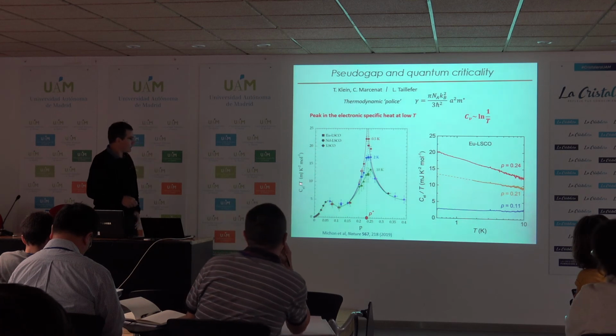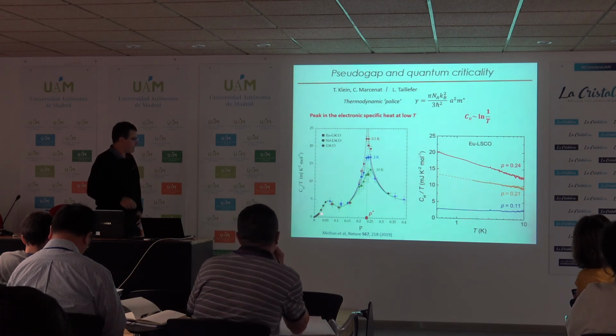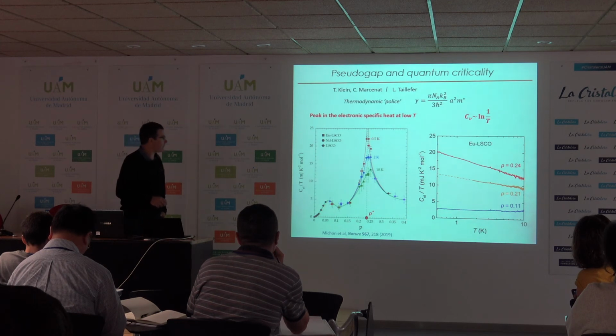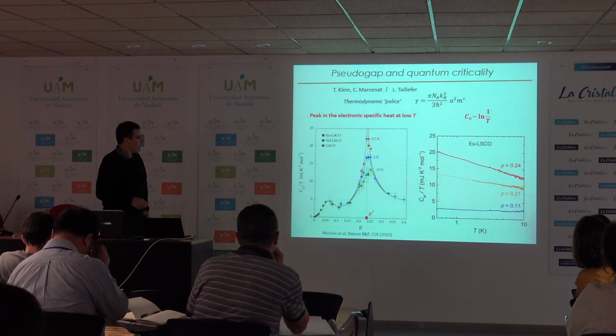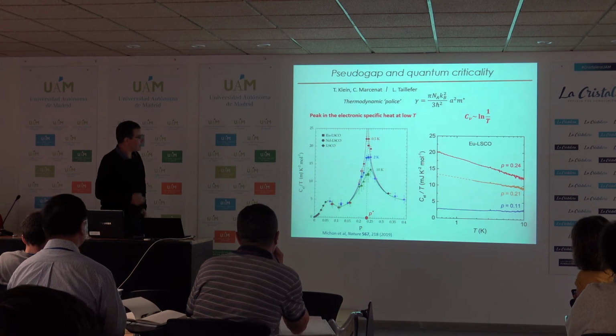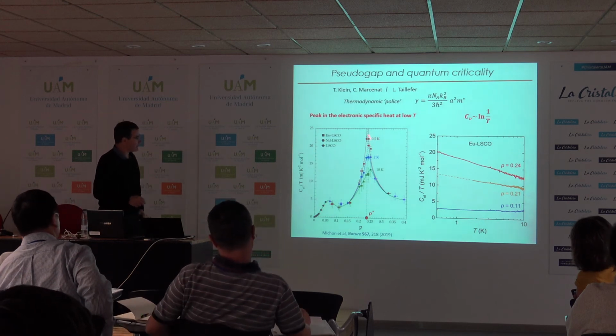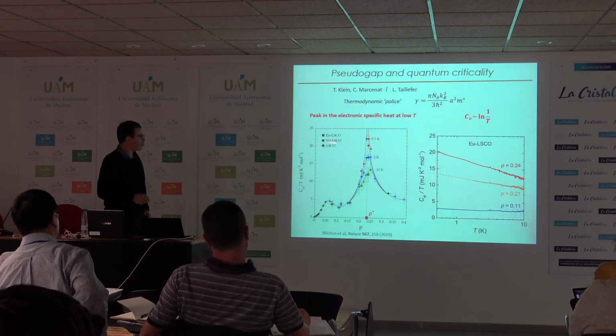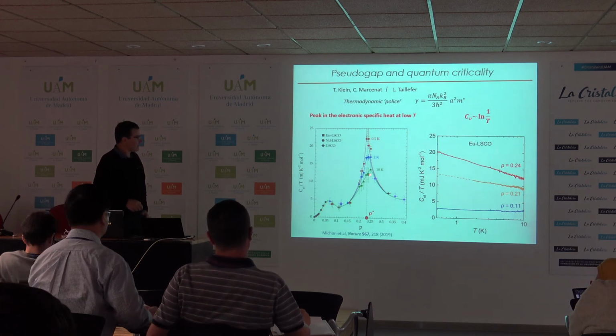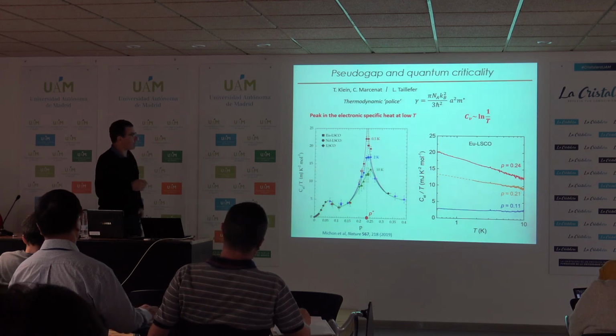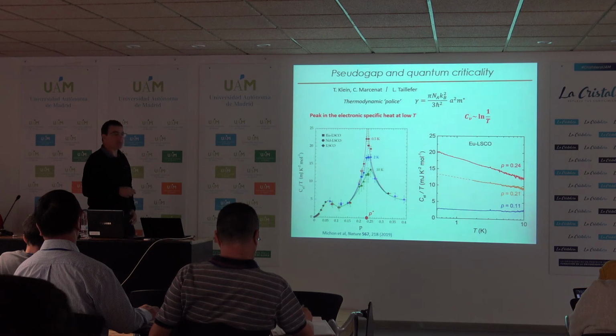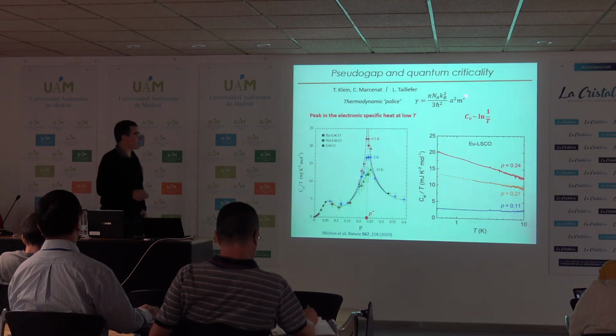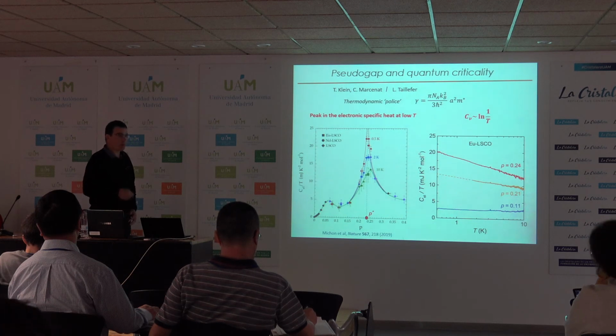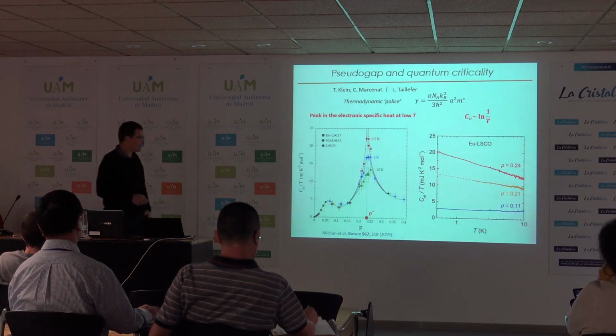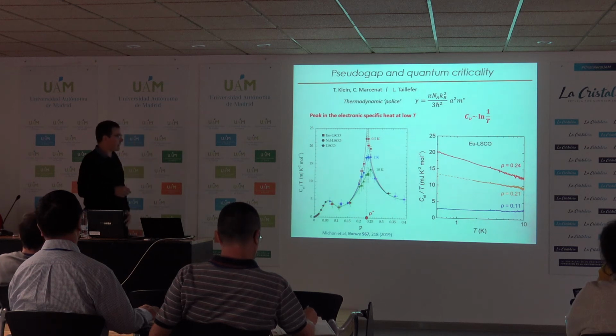Here I show you the specific heat divided by T versus doping, where the different colors correspond to the different families. What you see is that there seems to be a divergence of the electronic specific heat coefficient at the critical point of these two compounds, which seems to increase as you lower the temperature. The electronic coefficient of the specific heat is related to the density of states, so the effective mass. So this seems to point to a divergence of the effective mass at the critical point of the pseudo-gap.